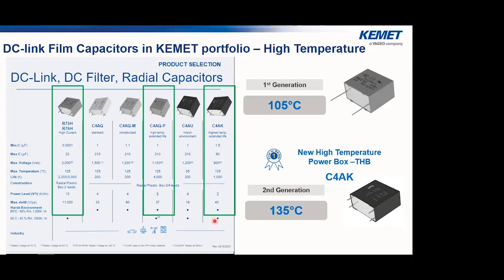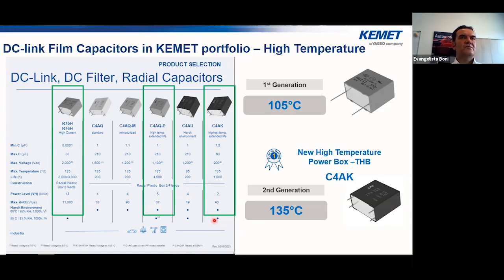Here we can see the current KEMET portfolio at high temperature. We have the new series in the green box: the R75H and R76H for resonant. They are also called DC link at high current, but they can be used also as resonant capacitors. Later on, we have the power box capacitors, C4AQP and C4AK. The first generation of the products in KEMET was set to work up to 105 degrees. Later on, KEMET came out with several capacitors increasing the temperature up to 125 degrees. The second generation can be considered like the C4AK that can work up to 135 degrees with a slightly different dielectric film that can permit working at very high voltage up to 125 degrees, but also to work up to 135 degrees.